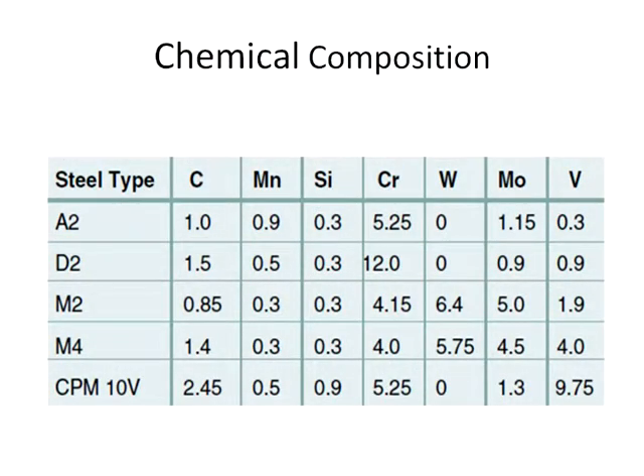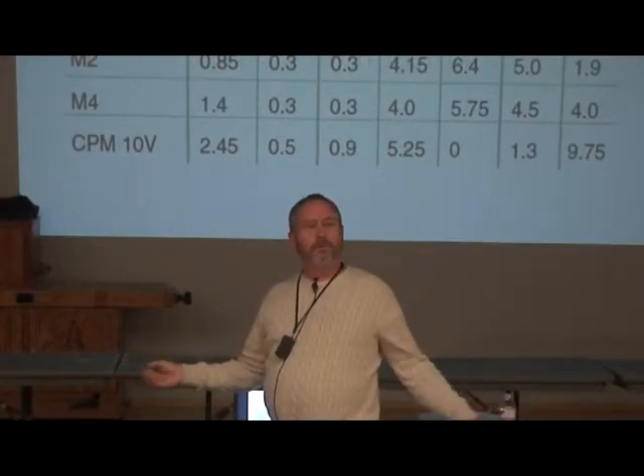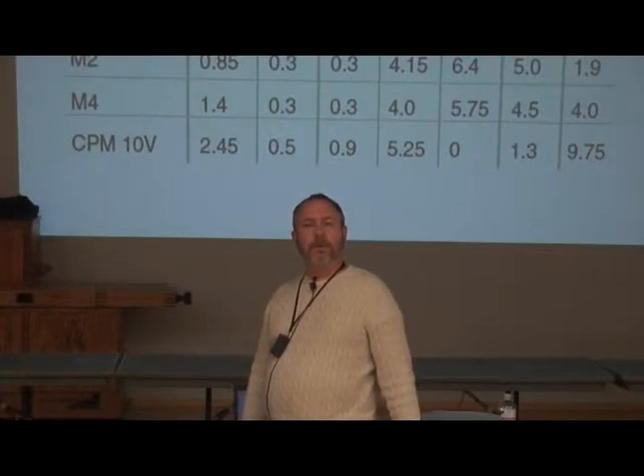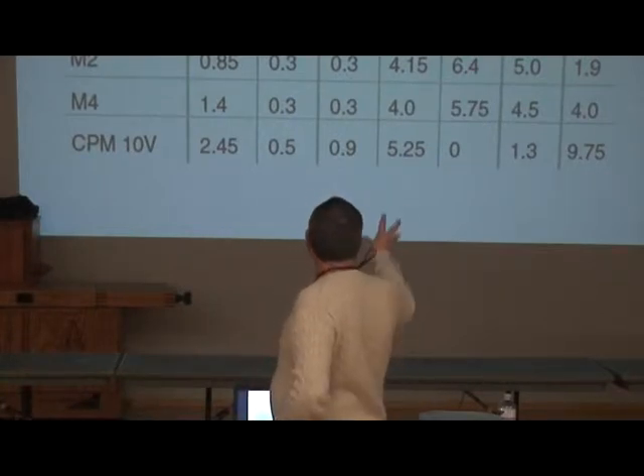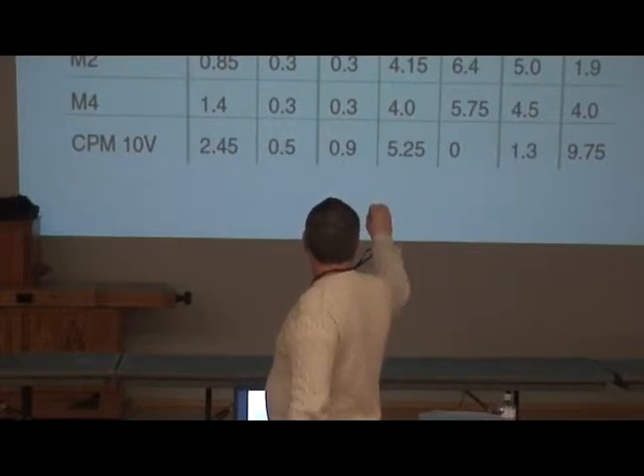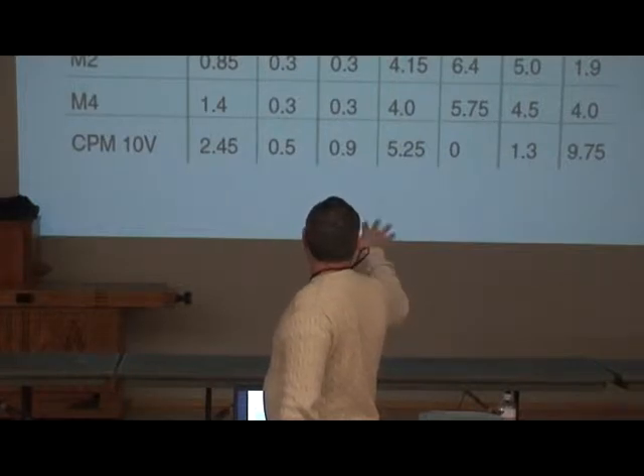Here are the typical chemistries. You can see the A1 has a good shot of chrome and some moly, or the A2. Your M2, M4s, your major ones are chrome. In fact, all of these have high chromes. Chromes are nice because they form carbides. You have chrome carbides, and another carbide former is your vanadium on the right. Tungsten also forms carbides. Moly is more of a strengthener, and it adds some toughness to the matrix. It generally doesn't form carbides. And all of those, when you make your steel, add certain properties to it.